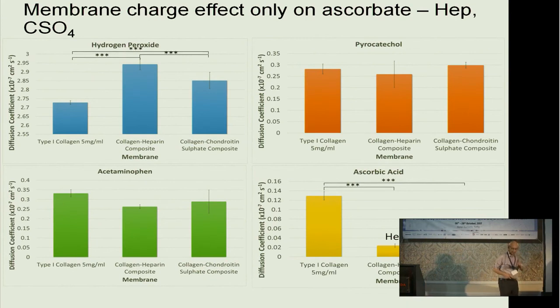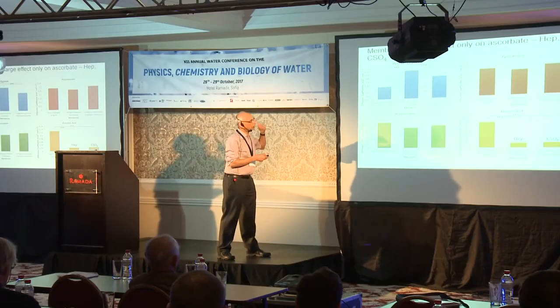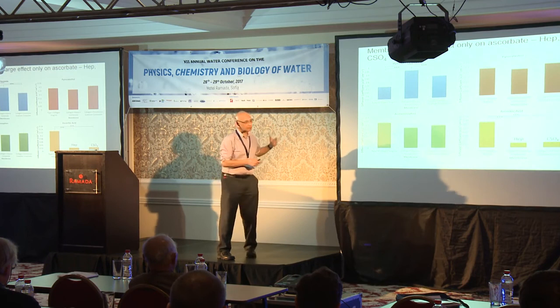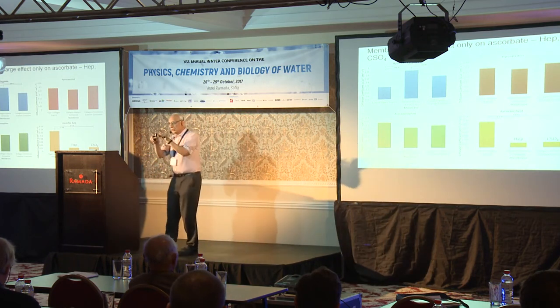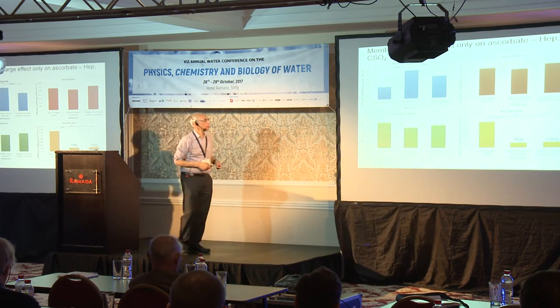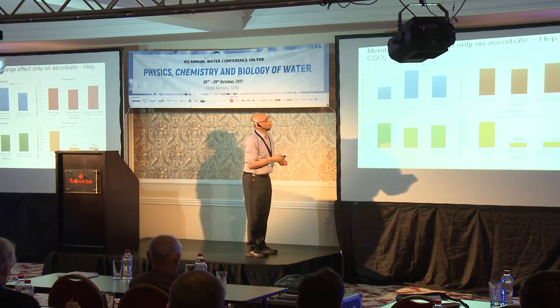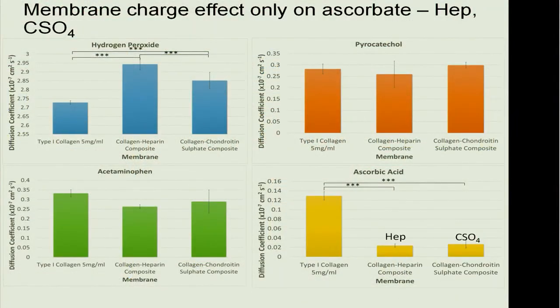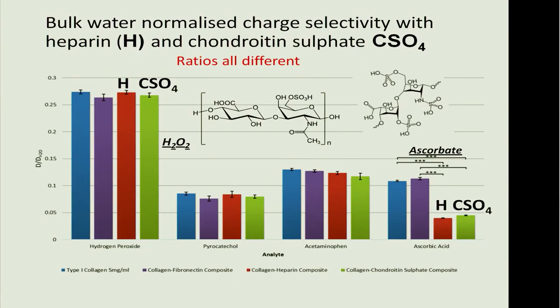But this is rather more understandable, thank God. It's a test for how valid our results are. So this is collagen heparin, and collagen chondroitin sulfate. It's approximating to the kind of tissue matrix that we have in our body. For a neutral molecule, there's not a lot in it when you throw in anionic species. But for ascorbate, which is anionic, you can slow down its diffusion using an ionic polymer inside the collagen. So that tells me something, that our measurements at least are valid, and on this occasion, reasonable.